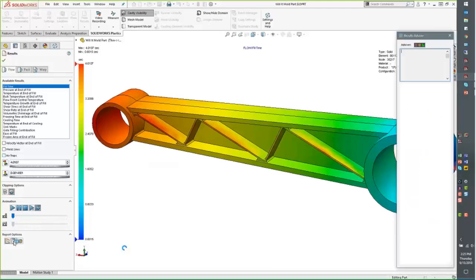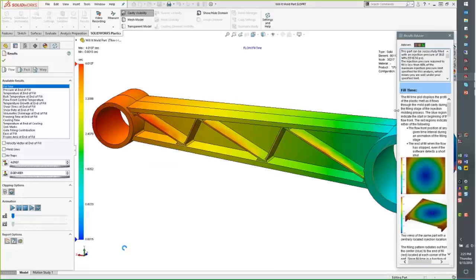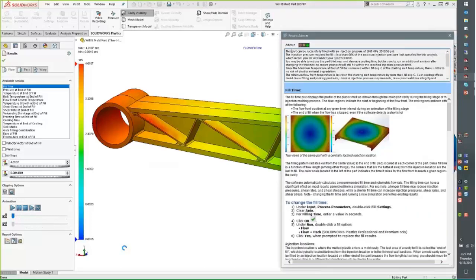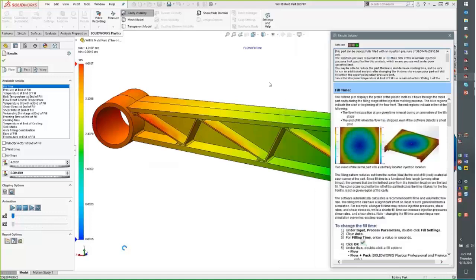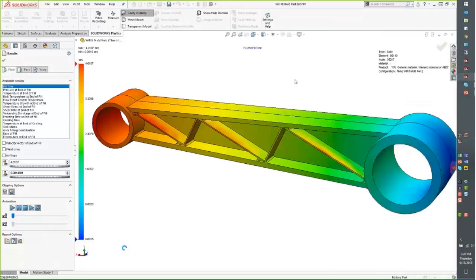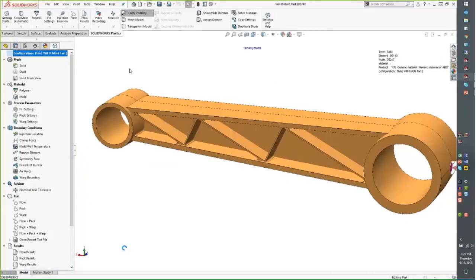And if we look at that solution advisor here, what we're seeing is we have the green light. So this is actually good. The part can be successfully filled with an injection pressure of 38 MPa. 100 MPa was our max. So we're within 66%. So as far as I'm concerned, with designing this part, I know that this can mold. So I feel pretty confident handing this off to the mold shop.